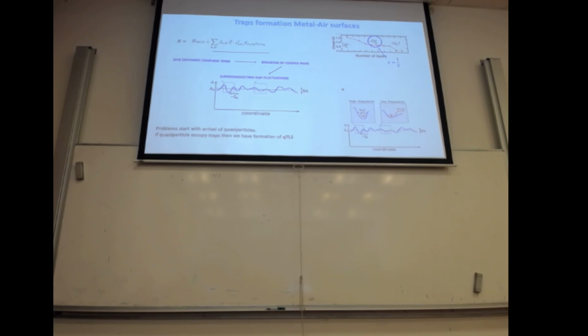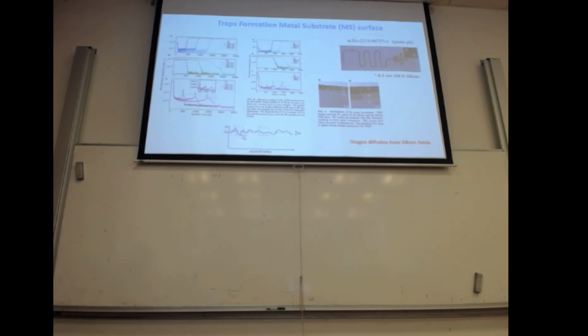And this means that these superconducting gap fluctuations are indeed sort of traps. And if we have some mechanism by which quasi-particles can come, then they can occupy these traps. And then the question is, can they create, for example, some two-level system, or just a trapped electron in traps that can be excited, and so on? And as we will see, the answer is yes, because unfortunately in our system we have an unwanted source of quasi-particles.